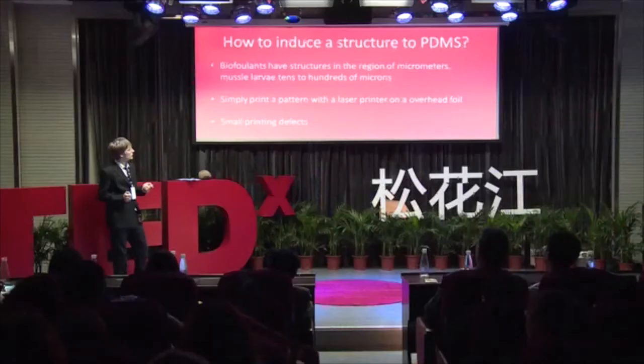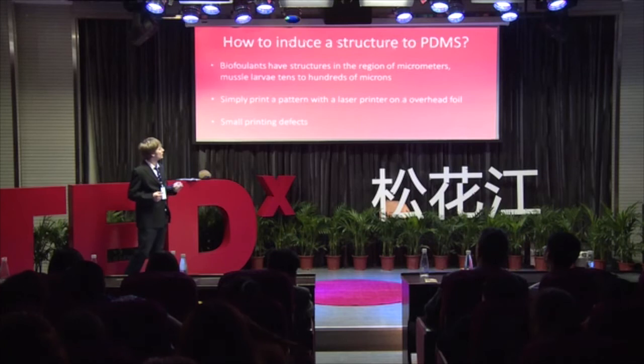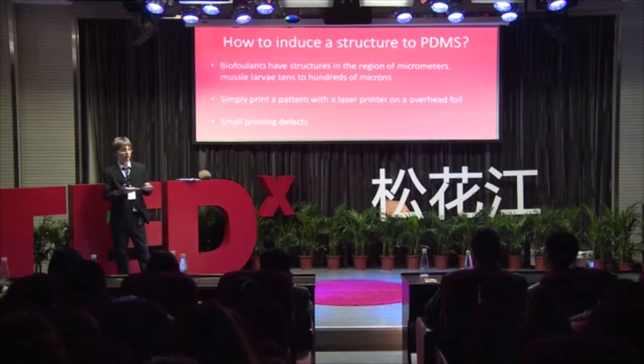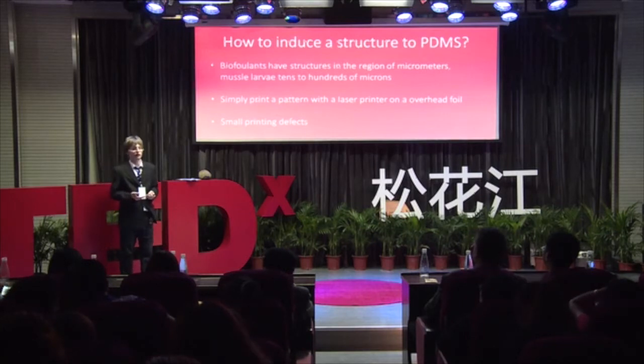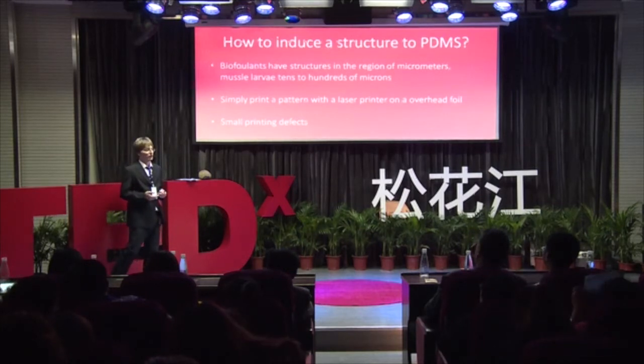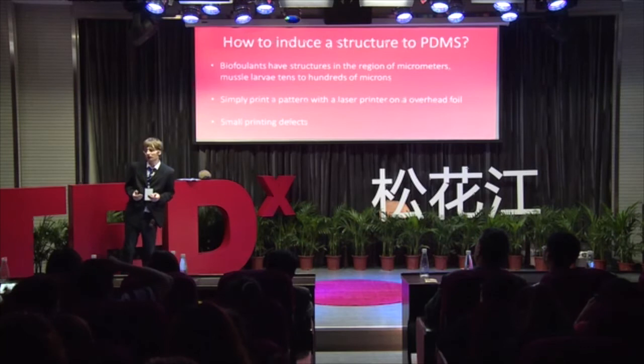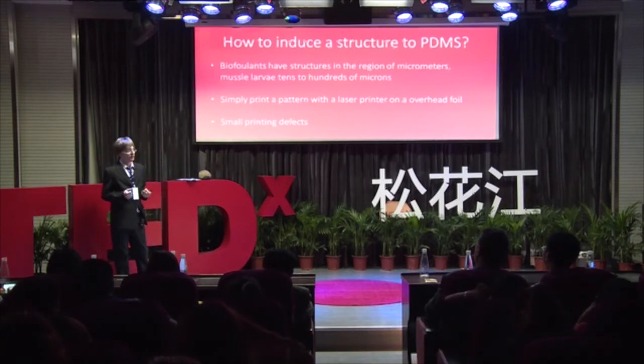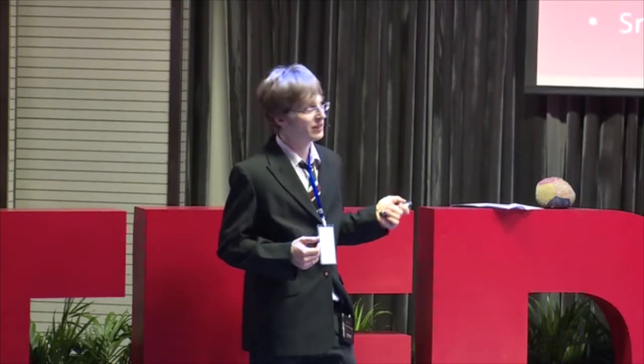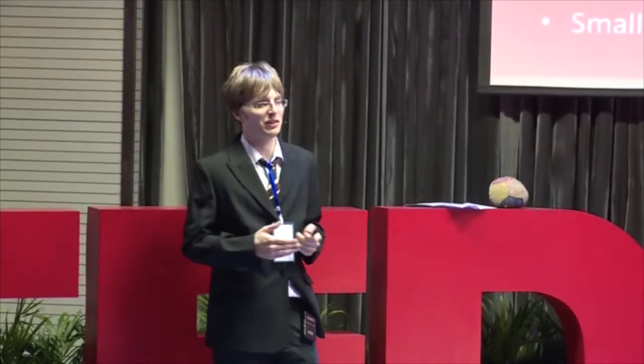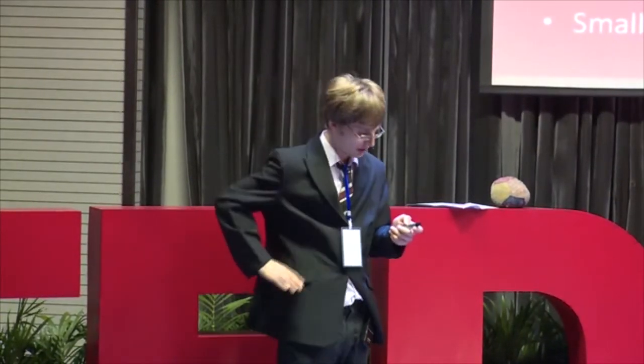And so, I first tried to create a big structure with my laser printer, and I printed on a commercial overhead foil. And the printer that I used was not so good, because the printer had lots of defects. So, by accident, I created a quite useful structure on a structure when I just wanted to create a large structure. So I'm quite happy about this.